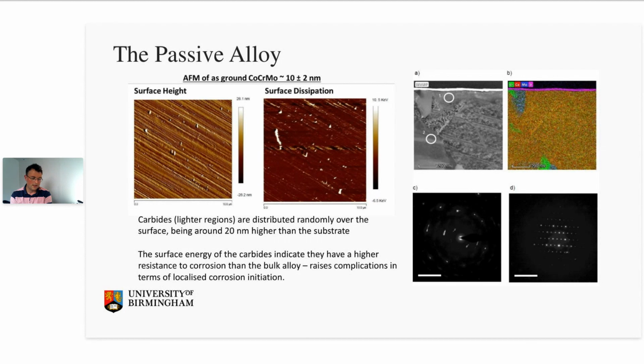But with that in mind, cobalt chrome surfaces also offer fairly complex interfaces and substructures that we need to bear in mind in terms of their degradation and their materials transformation mechanisms. So when we take a closer look, this is just a simple piece of ground low carbon cobalt chrome. Very basic alloy, fairly equiaxed grain structure, typically FCC based. But right at the interface, we have these nanocrystalline layers, which, when subjected to shear and fretting, are subject to dynamic rearrangement and recrystallization of those interfaces,